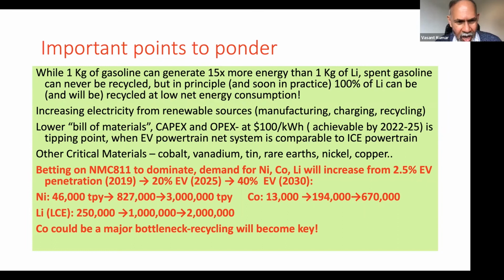And if the bill of materials is such that it's $100 per kilowatt hour, then the EV powertrain net system is comparable to an internal combustion engine powertrain. So that's a tipping point, and that tipping point is expected to take place within the next few years. There are other critical materials as well. I mentioned lithium, but really cobalt, vanadium, tin, rare earths, nickel, copper, all these are crucial in the development of battery technologies in the future.